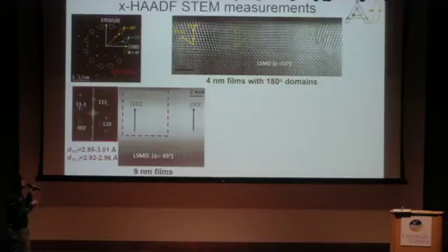In thinner films, we do see a domain structure. Here I'm showing 180-degree domains. And in thicker films, we in fact see the evolution of not just 111 out of plane, but domains with 001 out of plane. And this is perhaps the reason why the polarization of this is less than the polarization of thinner films. So if we calculate what the d-spacings are, the d-spacing of 111 is different from 11-1, and this is indicative of the fact that we don't have the conventionally reported polar orthorhombic phase. In orthorhombic phase, these are supposed to be the same things.